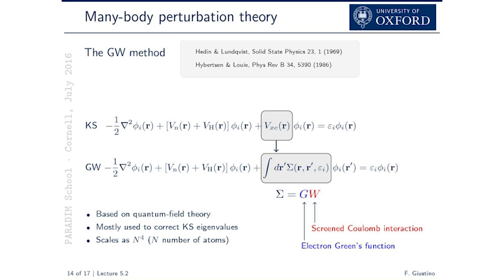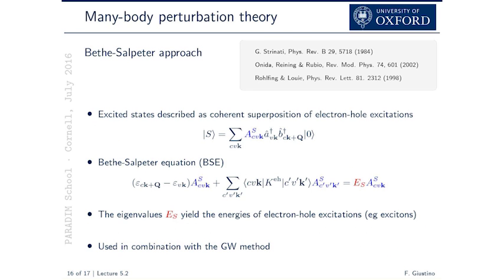Then, if you look at the example I was giving before of iron oxide, if in DFT it's metallic, there is no way that this will transform it into an insulator, because the wave functions have already been made into a metal, in a sense. You see what I mean? You cannot transform a metal into an insulator. So if the screening properties and the qualitative features of the system are completely wrong, this will not fix it. If the system is already insulating and you have a small gap, there is a very high chance that by using this, you will get a gap which is much closer to experiment.